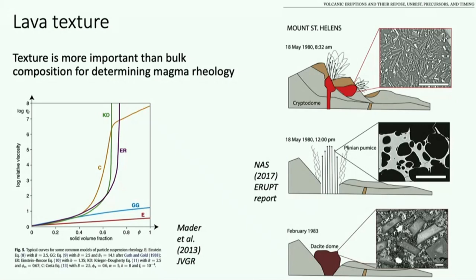But the point being that you can actually have lava rheology change by a factor of 1,000,000 as it crystallizes over a relatively small temperature range. And that can happen, in fact does happen, at many volcanoes. Anytime you have a basalt that erupted at 100 Pascal seconds, by the time it stopped moving, its viscosity was close to 10 to the 12 Pascal seconds. So it increased 10 billion times. And so that's what I'm really fascinated about studying, is how quickly these changes happen, and what we can tell from the morphology of the lava, what that can tell us about its cooling rate, and so on.